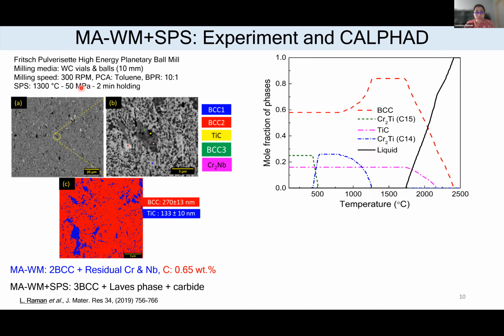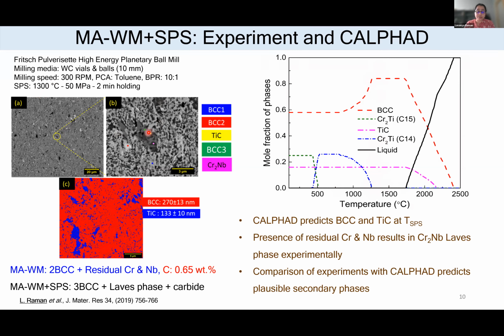Since our sintering temperature is 1300, at that temperature we have TiC and BCC, which is almost close to the experimentally observed phases. CALPHAD couldn't predict Cr2Nb because of the experimental conditions that we have. Here we have some residual elements which are not reflected in the calculations. Otherwise, we can say that CALPHAD predicts the major BCC phase and the possible secondary phase that we can have, which is really good.